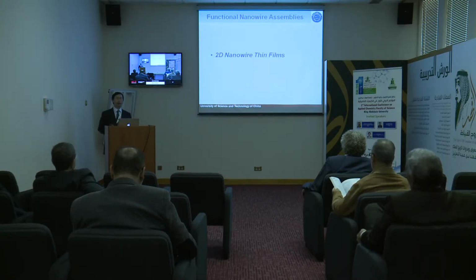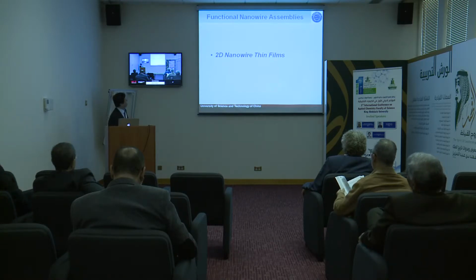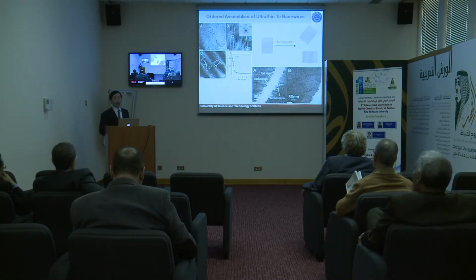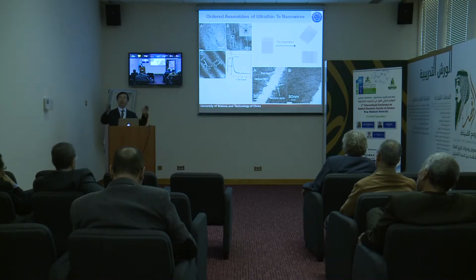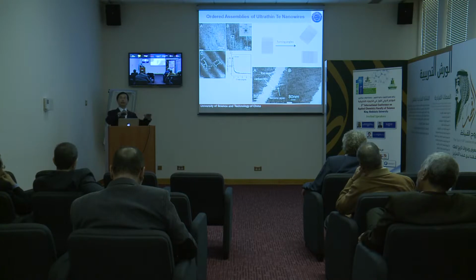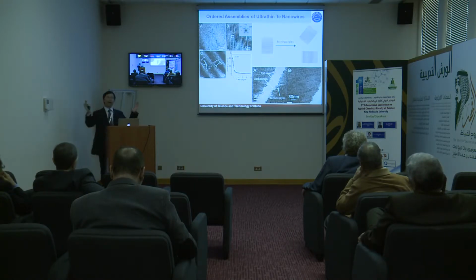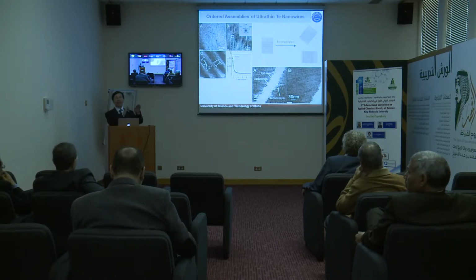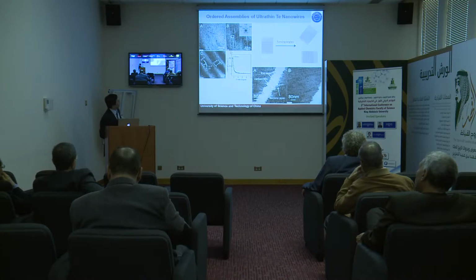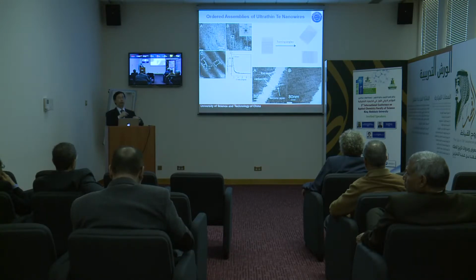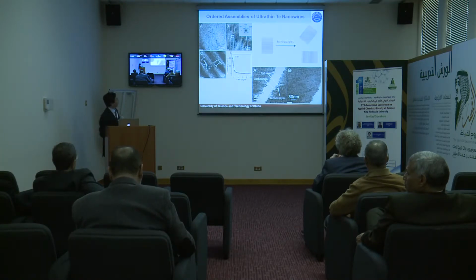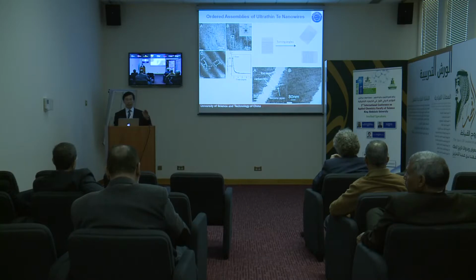Now, how can we get these nanowires to become ordered? I will show some data. We use these nanowires as building blocks to get a nanowire thin film, and the strategy is very easy. We use the traditional Langmuir-Blodgett technique. You float these hydrophilic nanowires on the surface of the air-water interface, then you apply compression. You make these nanowires highly aligned along the same direction so that you get a monolayer nanowire thin film. You can deposit a second layer at a different turning angle. You can construct nanowire thin films with different layer numbers, and you can also use small-angle X-ray scattering to identify this ordered structure after you assemble them.